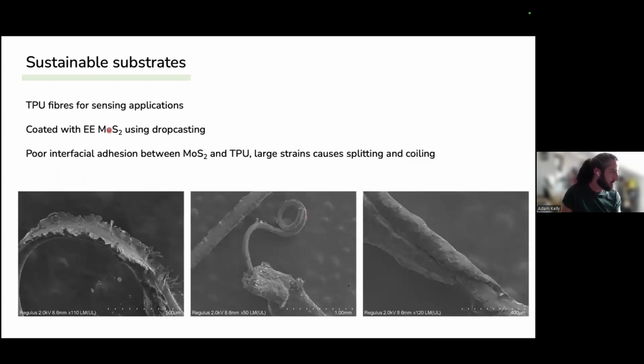So she wanted to use TPU fibers for sensing applications. So these were first coated using drop casting directly onto the fiber. And what we found was poor interfacial adhesion between the MoS2 network and the TPU. So the TPU underneath basically moved independently of the MoS2, and it caused all this pile up and all this breakup. It was pretty ugly. The strain of the TPU itself caused the entire structure to split and coil.